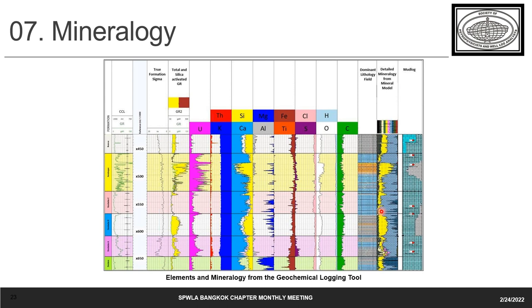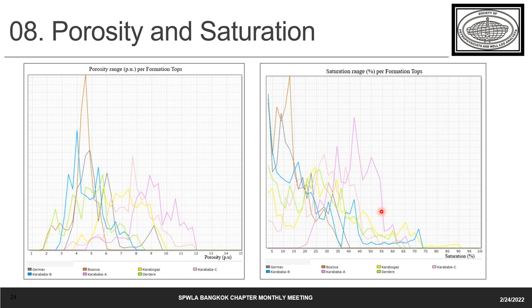While for the carbon oxygen, the quality is obtained by comparing the average value of the three passes with the numerous stationary measurements that were taken during the logging. And also we have carbon oxygen for detectors 1, 2, 3, and 4, and calcium silica ratio again for all four detectors.